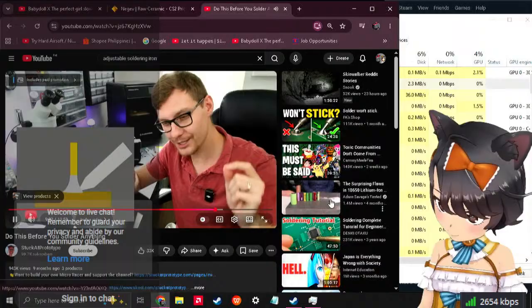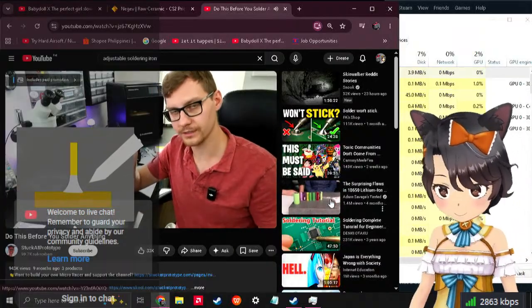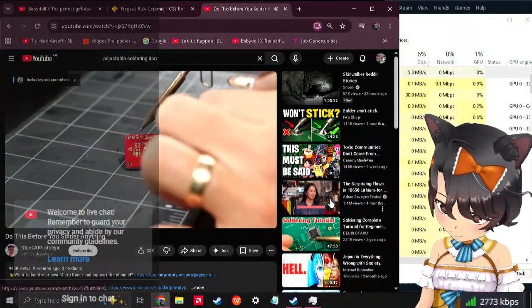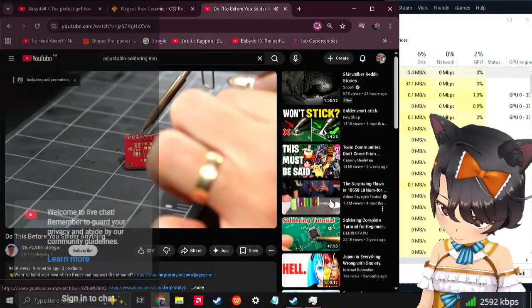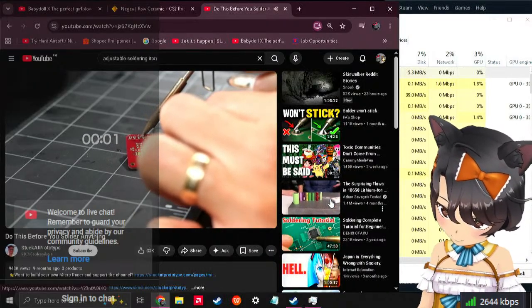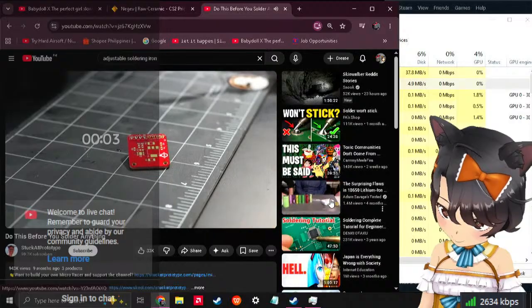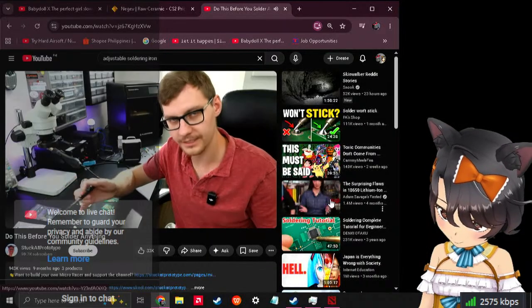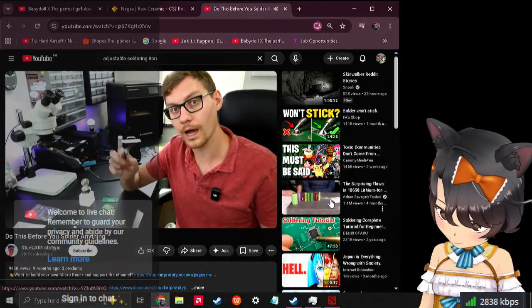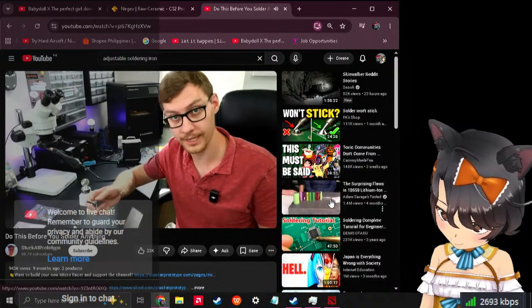You're melting the solder with the joint, not with the iron. Now, if this step is taking longer than 3 seconds, that means your soldering iron is not hot enough. But if it is charring and burning, that means your iron is way too hot. So that's how you know if you have to go up or down in temperature on the iron itself.